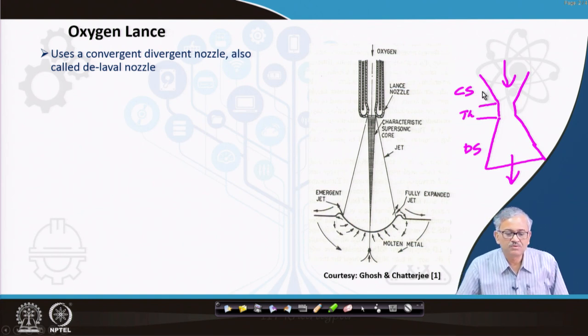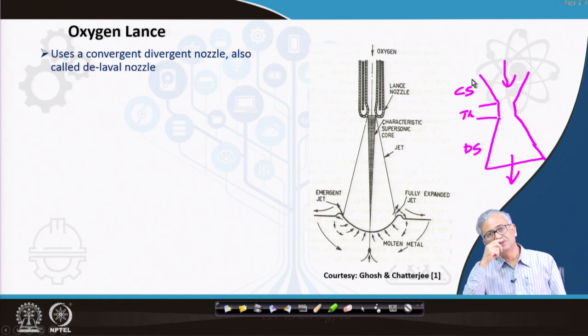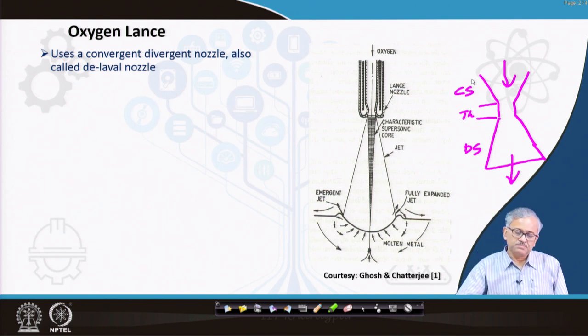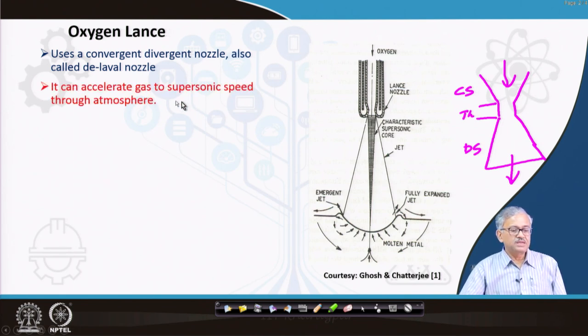But if you want to produce the oxygen jet through a cylindrical nozzle, the oxygen will come out at a very high pressure, and it will dissipate energy by shockwave generation. So, this is the thing: a convergent-divergent nozzle can accelerate the gas to a supersonic speed through the atmosphere. That is the main advantage of using this convergent-divergent nozzle.